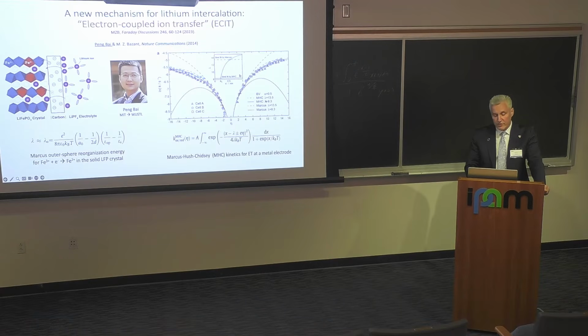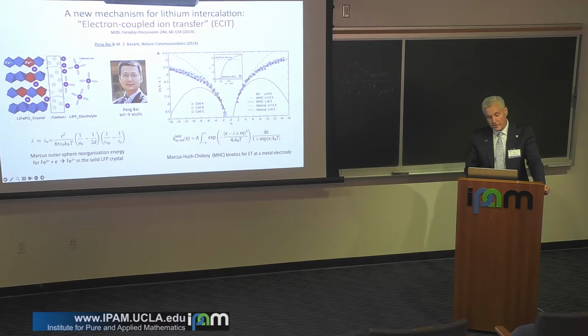The lambda, or the reorganization energy, controls the curvature of the Tafel plot. So basically, if you plot log of current versus overpotential, it's curved, and it's not Tafel's law. And it's a perfect fit.